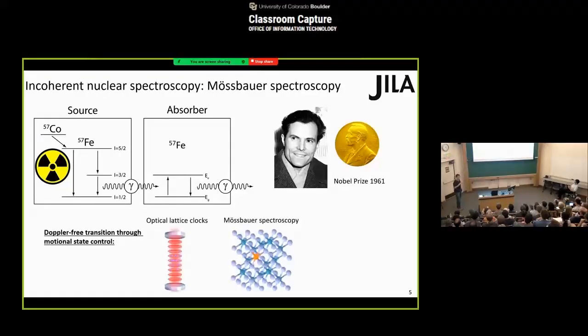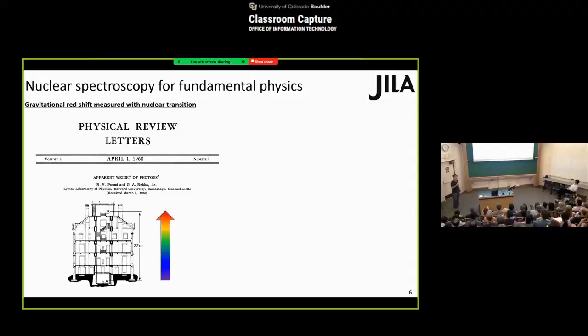A very unique character of this Mössbauer spectroscopy is that one can observe very narrow transition lines, essentially free from Doppler broadening. Now, this is very similar to what we do in modern atomic AMO systems, where we use optical lattices or lasers to confine the atoms very tightly. And in Mössbauer spectroscopy, we can rely on the crystal structure inside a solid to provide the same type of confinement, where we can eliminate the Doppler broadening and the recoil shift. So these Mössbauer spectroscopy, nuclear spectroscopy techniques can be very useful for fundamental physics.